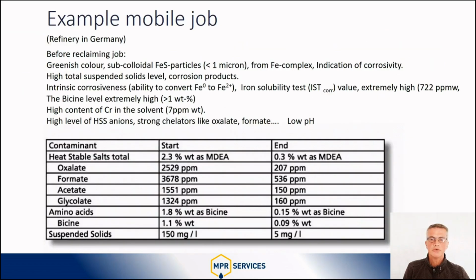A German refinery contacted us. They had corrosion and plugging issues. The technology group of the oil company had done amine analysis and reported colloidal iron sulfides, high iron solubility, high levels of bicine and heat stable salts, and because of that the pH was low. The chromium level was high, and not surprisingly there was a lot of suspended solids. The amine color was green.